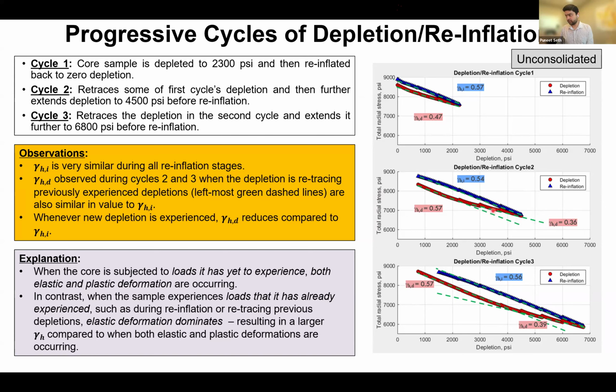Again here, whenever new depletion that was not seen in the previous cycle is performed, or the sample is subjected to that, the depletion coefficient is much lower. Same here. Whenever it sees new depletion, the depletion coefficient is much lower. And a very important thing, this is again an unconsolidated sample, right? So what is going on here? The explanation goes like this. When the sample is subjected to loads that it has not experienced before, both elastic and plastic deformation are occurring. And in the case of unconsolidated rocks, plastic deformation can dominate depending upon how much depletion you subject the sample to.